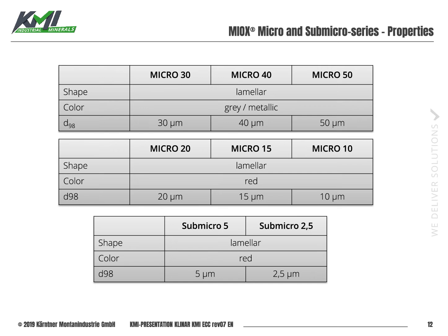Now when you look at the grades, we start with a Micro 50, which is the coarsest micronized grade, down to the finest one, which is called Sub-Micro 2.5. It's easy to read. The name of the micronized grade is always the D98 of the particle size distribution. So that means, for example, when you look at the Micro 30, the D98 of the particle size distribution is